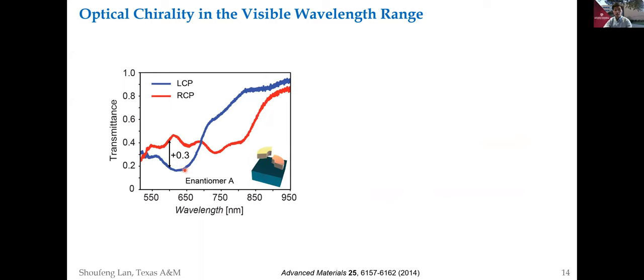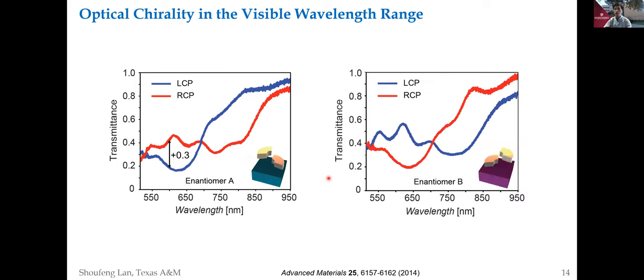This is because it's the enantiomer A. And on the other hand, if we use the enantiomer B, which is the mirror image of enantiomer A, the spectral behavior will flip. For example, again, at the wavelength of around 600 nanometers, the transmission difference between RCP, the red curve, and the LCP, the blue curve, is minus 0.3.